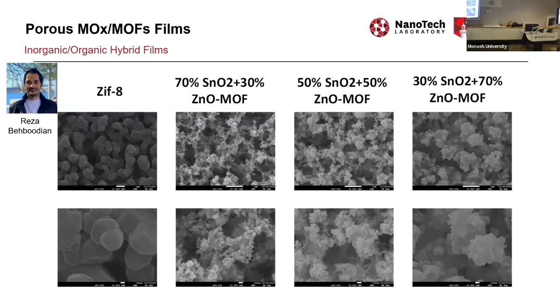If we expose it to a large amount of ligand, and by large I mean like one gram, and leave it long enough, the entire zinc oxide will be converted into ZIF8, but you can do partial conversion as well. What we did was create a mixture of zinc oxide and tin oxide, because with flame, as long as they dissolve in a solvent, you can mix different precursors and create a composite.